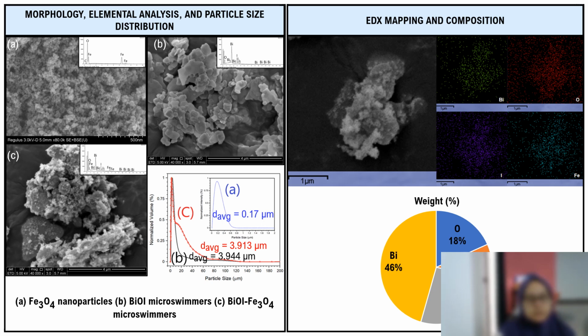This figure shows the morphology, element, and particle size distribution of the magnetic nanoparticles and microswimmers. It can be observed that the magnetic nanoparticles have a spherical shape with an average size of 0.17 micron. Meanwhile, the bismuth microswimmer has a plate-like shape with a smooth surface and an average size of 3.944 micron. Whereas the bismuth magnetic microswimmers have a rougher surface with the magnetic nanoparticles coated on the surface, and the average size obtained is 3.913 micron.